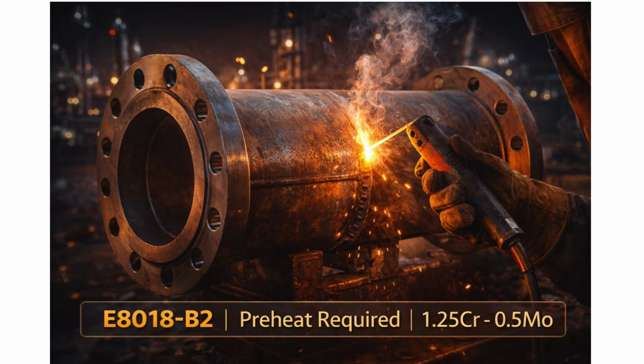Take E8018-B2. E: electrode. 80: 80,000 psi minimum tensile strength. 1: all positions. 8: low hydrogen iron powder coating, AC or DCEP. B2: chrome moly alloy, 1.25% chromium, 0.5% molybdenum. This electrode is widely used in petroleum refinery piping and high-temperature pressure vessels.